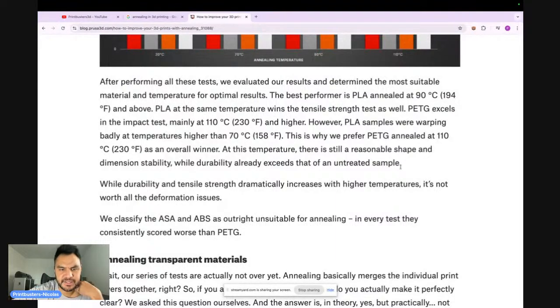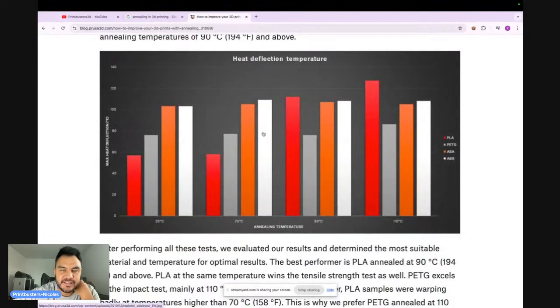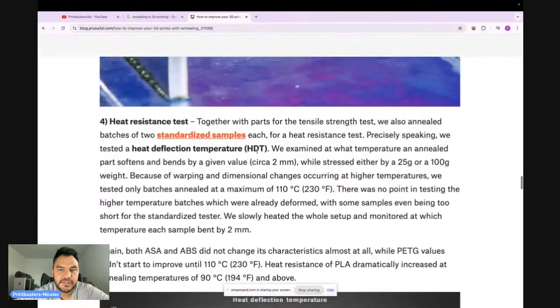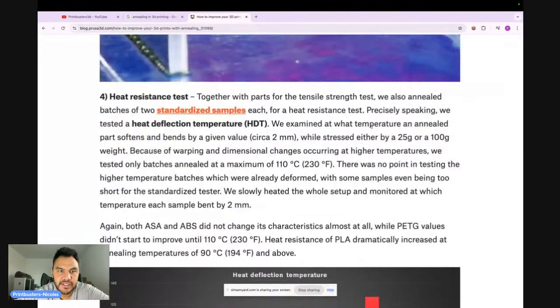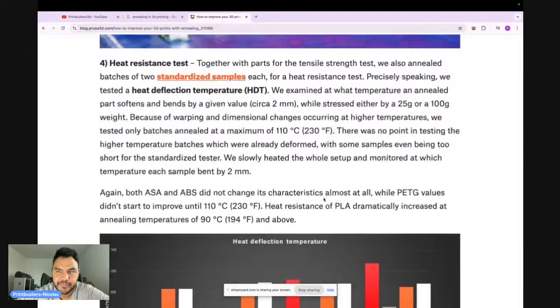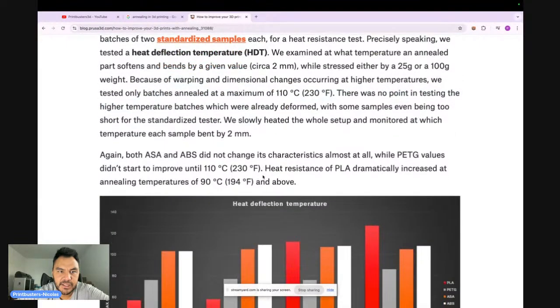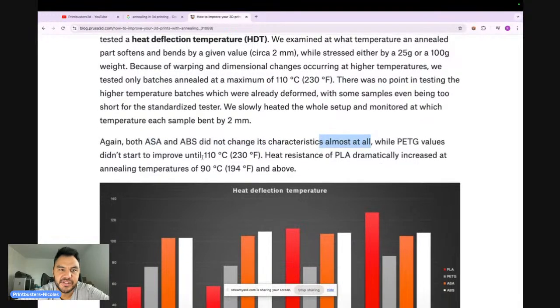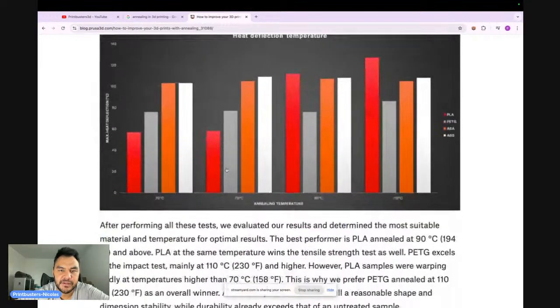But let's see how they explain that, because ABS, ASA is not going to crystallize. So basically, when you anneal ABS and ASA, there's nothing much that will change that will increase its HDT in theory. So let's see how they explain this. Both ASA and ABS did not change its characteristic almost at all, while PETG value didn't start to improve until 110. Heat resistant PLA dramatically increased annealing, okay.